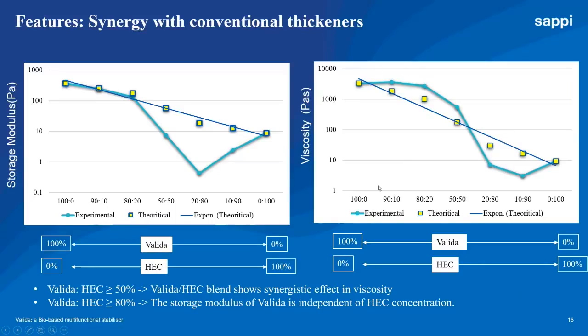Here we can note the synergy between Valida and indeed HEC. When Valida is in formulation with HEC at a dosage higher than 50%, we can notice that there is indeed a synergy between these two ingredients, leading to a boost in viscosity. And what does this mean? Well, this means that when adding Valida in the formulation, this can potentially lead to a lower dosage of HEC while still achieving the target viscosity and benefiting also from the outstanding features of Valida in terms of stabilization performances and also mechanical reinforcing, as we will notice later.